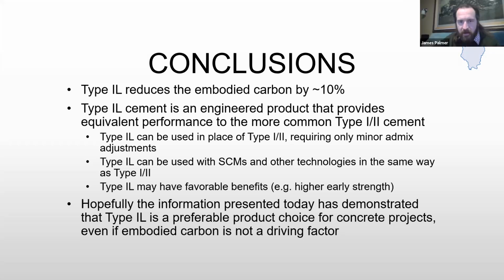Yeah, I am not finding the slide I thought I had, but overall they're very similar. From memory, your standard concrete is typically on the order of 2,000 surface resistivity. When you get into lower permeability specification requirements, those set points are rather drastically reduced. I believe it goes down to like 1,200 before you get into the lower permeability mixes. For the PLC, the particle packing helps. So it's very similar, but by 28 days, you might be a percent or two different. And again, it's going to vary depending on whose cement it is, but a 2% change there is not enough to impact your performance testing.